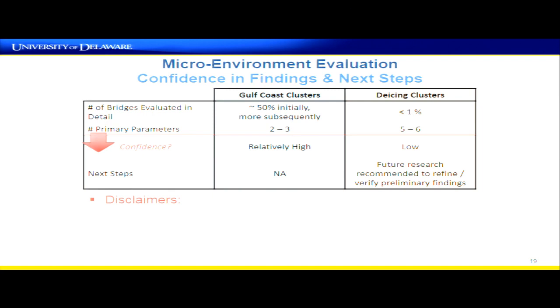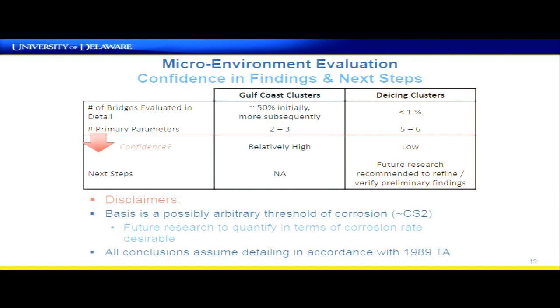A couple of disclaimers on this. It's based on a possibly arbitrary threshold of condition state 2, meaning that we don't know what that means in terms of corrosion rate. To quantify this in terms of corrosion rate would be a much more thoughtful and engineered process that we simply don't have the data to evaluate right now. This also assumes all conclusions are based on bridges that were detailed according to that 1989 Federal Highway Technical Advisory. So everything in there we're recommending to continue to be implemented.